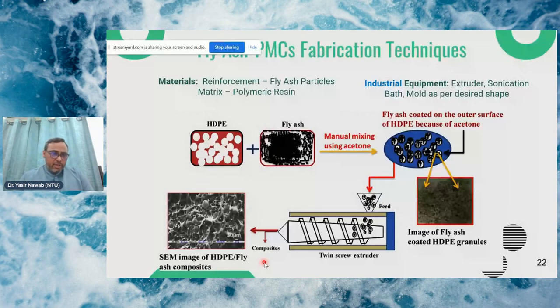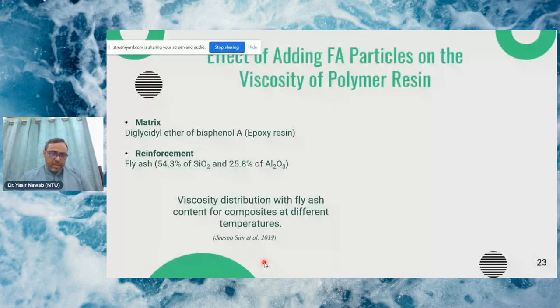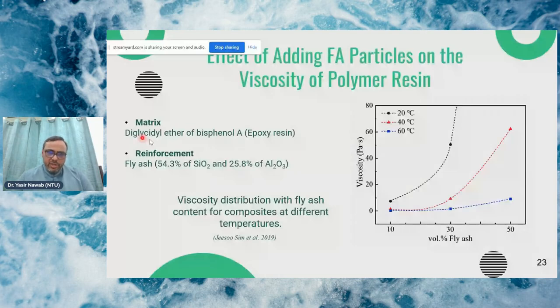There is another example, it's with epoxy, a thermosetting resin, and fly ash. In fact, it was used along with it at various percentages. When we are working with a thermosetting matrix, another problem is that when we add fly ash into the matrix, the viscosity of the matrix increases. For example, if we increase the volume percentage of fly ash that we are using in the matrix, there is an increase in viscosity. This increase in viscosity can be controlled for a specific time by increasing the temperature. So this was done for three temperatures: 20, 40, and 60 degrees centigrade. At 60 degrees centigrade, the effect of the increase in viscosity for a limited time, you can say for 1 hour, is a sufficient window in which we can do our manufacturing.